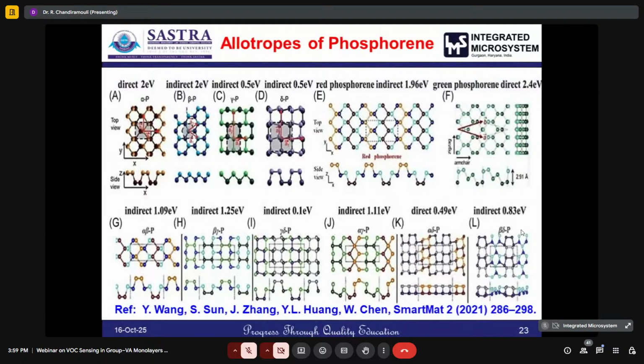Alpha is a direct energy band gap, and gamma and delta have an indirect band gap of 0.5 electron volt. Apart from that, red phosphorene has an indirect energy band gap of 1.96 electron volt. Green phosphorene also exists with a direct band gap of 2.4 electron volt. The other combinations, alpha beta phosphorene, beta gamma phosphorene, gamma delta, gamma alpha phosphorene, alpha delta, and beta delta phosphorene, are also possible.